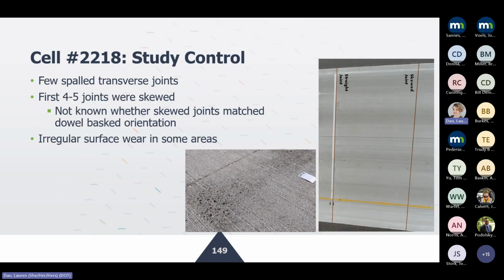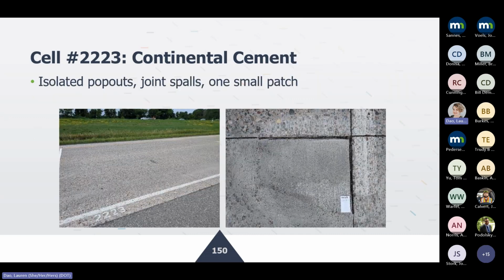Study control, you wouldn't expect to see anything. And this cell was not diamond ground. You do see the turf drag texture right there. And then we did notice that the first 4 or 5 joints were skewed, maybe at a 10-degree angle. I don't know whether this was done to intentionally mask dowel basket orientation, or whether the sawing crew just wanted to have some fun out there. I don't know what the issue is. But anyway, we did notice that the first 4 or 5 joints were skewed.